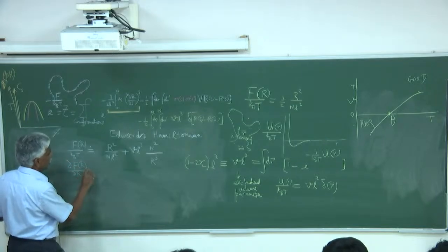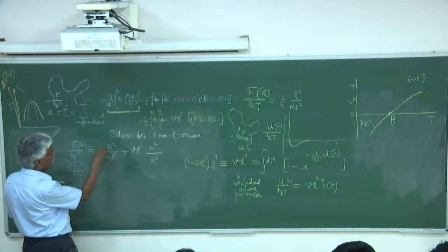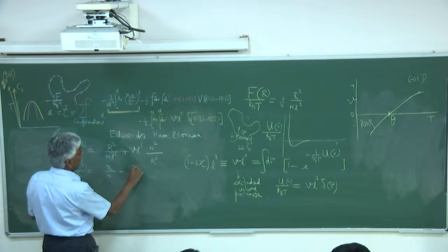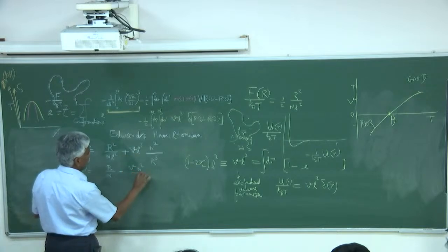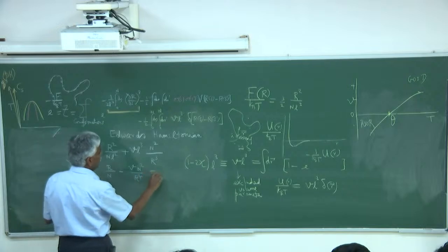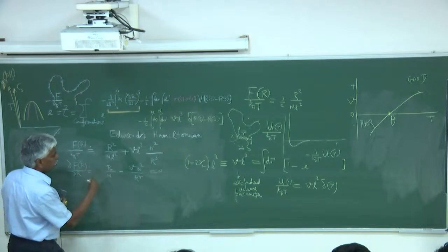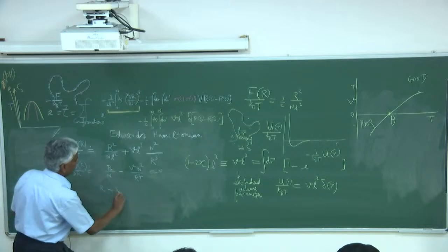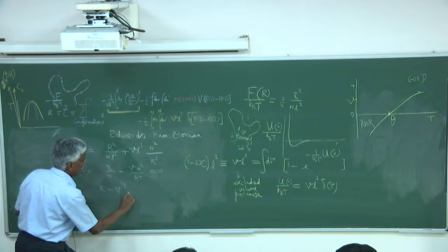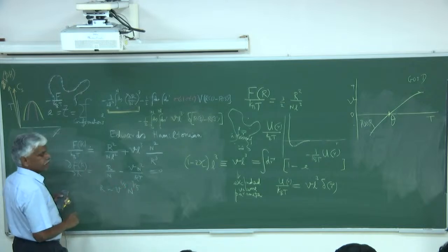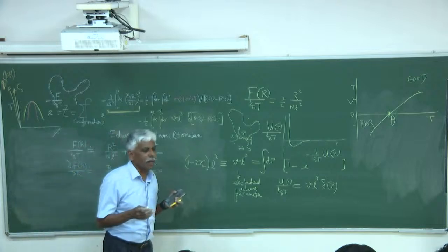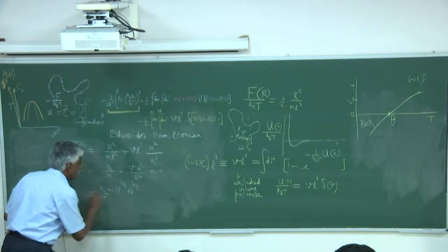People get Nobel Prizes for this kind of calculation. Flory, and this is called Flory radius, Rf. Flory is another Nobel Prize, right? Same Flory again, that guy. Rf goes like n to the 3/5. If it goes n to the 3/5, you know the exponent nu is 3/5. I already told you, then the structure factor S of k will go like k to the negative 5/3. Fractal dimension is a reciprocal of nu, I told you, as 5/3.